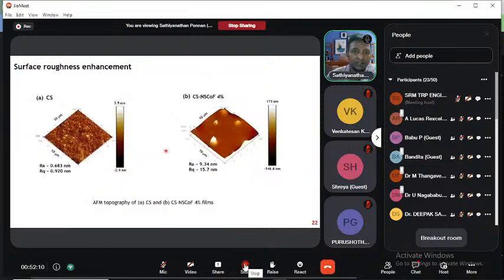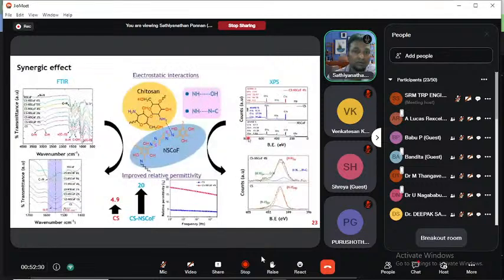So this is the proof for the surface roughness. You can see this is the neat chitosan, and this is chitosan calf. The neat chitosan does not have much surface roughness. The height of the roughness is about 3.9 nanometers, but in this case it is 173 nanometers. So it has higher surface roughness. That's why it produces good performance.